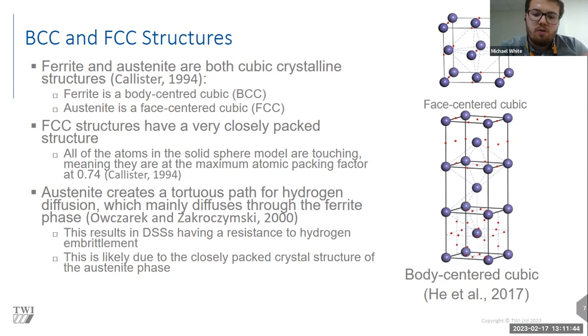The densely packed structure of austenite is what causes the slower diffusion rate within its structure and creates a tortuous path for hydrogen, which mainly transports through the ferrite phase of duplex stainless steel, avoiding the austenite islands, which can act as hydrogen sinks. This gives duplex stainless steels a resistance to hydrogen embrittlement, giving them a significant advantage for processes involving hydrogen.